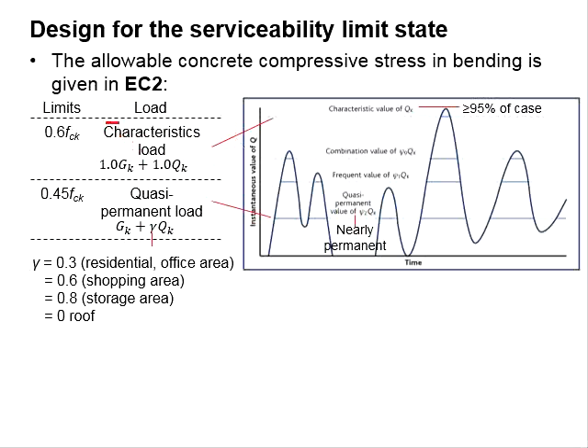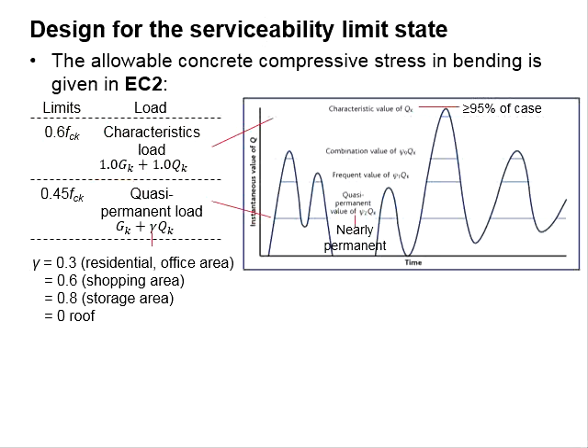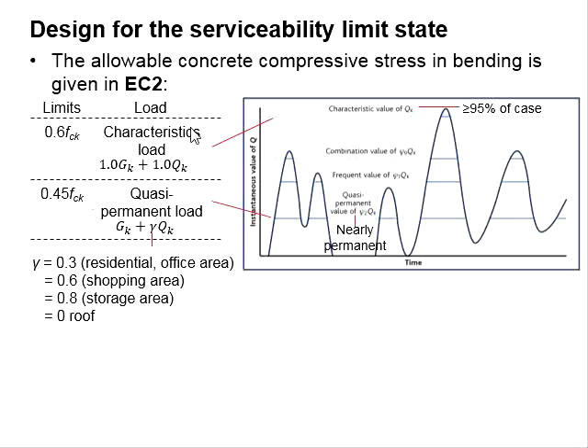Under the characteristic load, where 1.0 GK and 1.0 QK is applied, the limit is set to be 0.6 FCK. While under the quasi-permanent load, the 0.45 FCK is set as the limit.